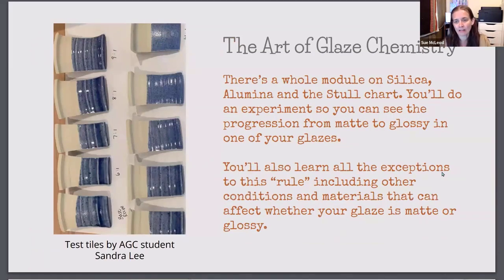So in the Art of Glaze Chemistry, there's a whole module on silica, alumina, and the Stull chart. And you'll do an experiment so you can see for yourself the progression from matte to glossy. And so here, these are by Sandra. Starting here, this has the lowest silica level, and this is a matte glaze. She added a bit of cobalt for color.